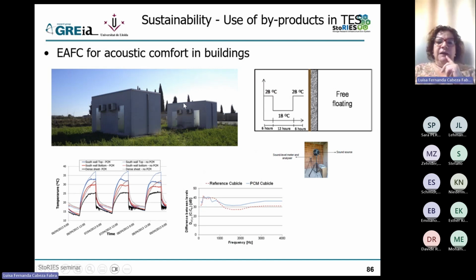And here we put the material in the inner wall, internal wall, you see. And we equipped the side where in a room we could change the temperature, so really controlling the different temperatures, day and night, and winter and summer. And on the right side, we had free floating, and it's where we were measuring the behavior, which is the figure you see in the bottom. Again, the reference cubicle was a standard commercial membrane, and the PCM cubicle is our newly developed membrane with PCM in it. And we could see a difference. This is from the thermal point of view, and also, as you can see, we also measured, of course, the acoustic performance.